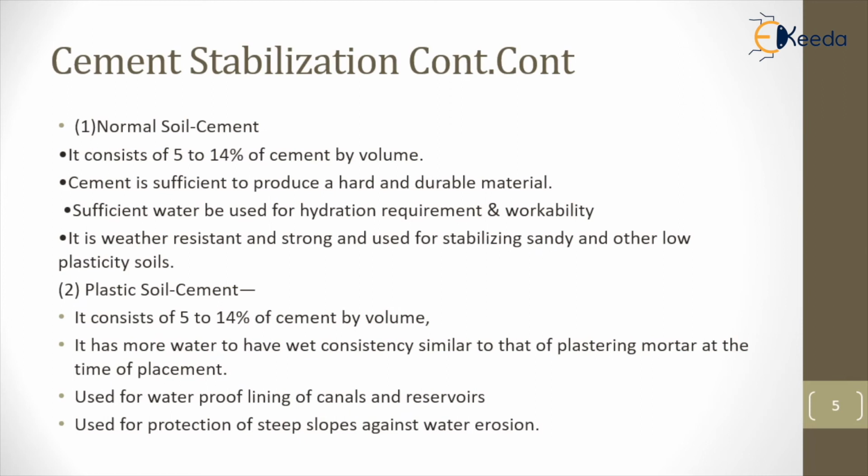Next, when plastic soil is mixed with cement, it consists of 5 to 14 percent of cement by volume and has more water compared to normal soil. It can be used for waterproofing the lining of canals and steep slopes to prevent water erosion.